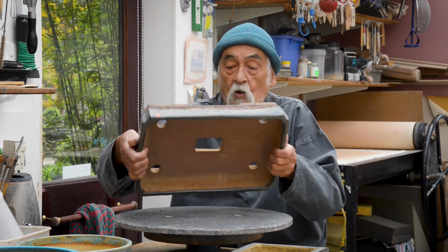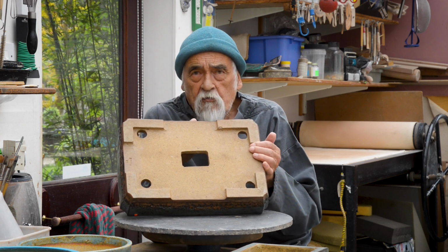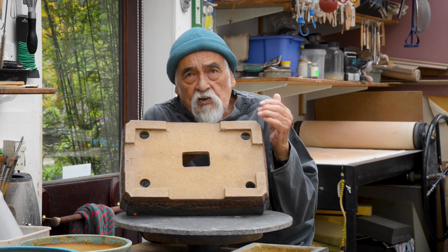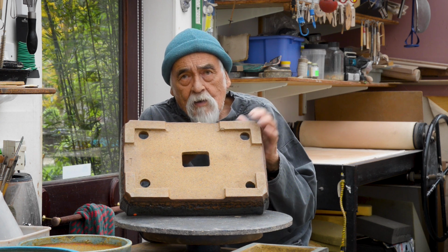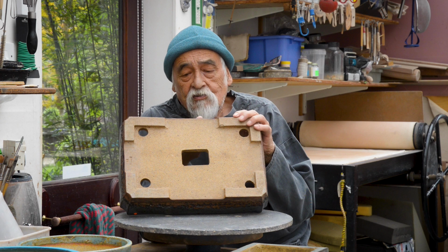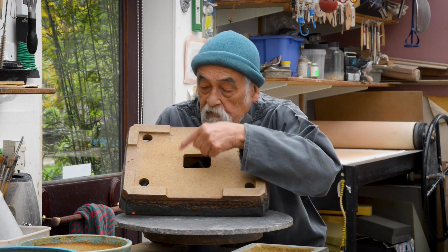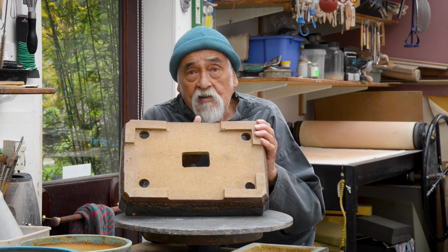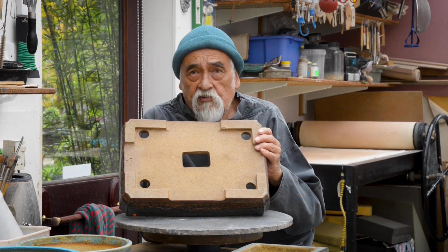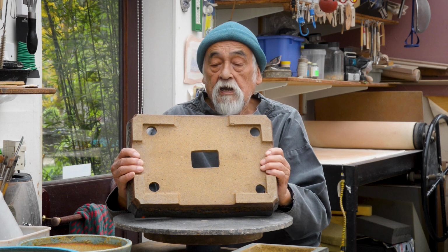but it's very heavy. This pot was also reduction fired, and what is interesting is what happens when you fire in a gas kiln, at a certain point all of the air gaps are sealed, so there's no air in the kiln, and for the gas flame to continue, it's got to get its oxygen from somewhere. So it gets its oxygen from the oxides, etc., in the glazes and in the clay. And you can see how you've got these little dots of the iron which become apparent, and also the clay-based body is considerably darker than you get in an oxidized or electric kiln firing. I love this pot. It's one of my favourites.